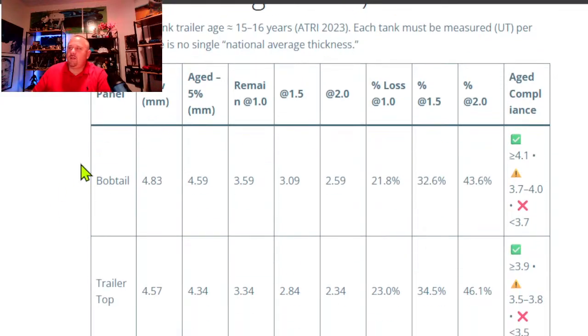Looking at this, new bobtails are 4.83, aged 4.59 millimeters thick remaining. If you remove 1 millimeter of material, you're left with 3.59. If you come over here and look at these numbers, if you're greater than 4.1 millimeters thick, you're in the green.